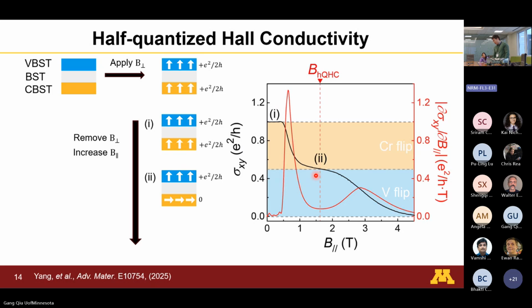So what that gives you is that the chromium layer doesn't contribute any Hall signal anymore. So you only have a half-quantized top surface that gives you about 1/2 of the sigma xy. Okay, so this is a half-quantized Hall plateau. Even though I call it a plateau, you can see it's not a very flat surface. We still have some material improvements that need to be optimized, but you can see if you take a derivative of this curve, it sits right here at about 1/2 of the quantization, right?